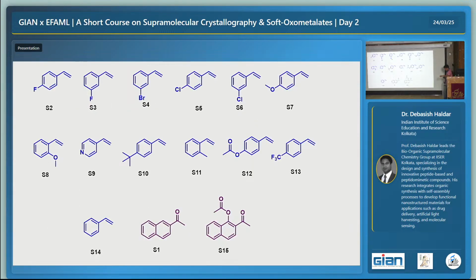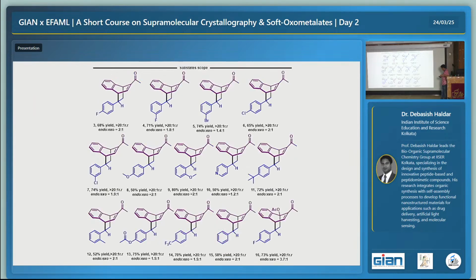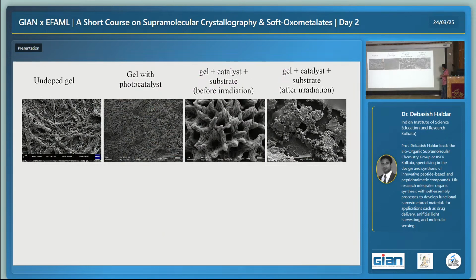And so we have studied the different substrate scope, and this reaction is happening with different substrates, with almost 68 to 72, 73% product in some cases. And then we have studied the morphology of the gel before and after reaction. So this is the undoped gel, that is only gelator. And then with the photocatalyst and the substrate, the gel looks like that. After light irradiation, when the gel melted, it looks like that.